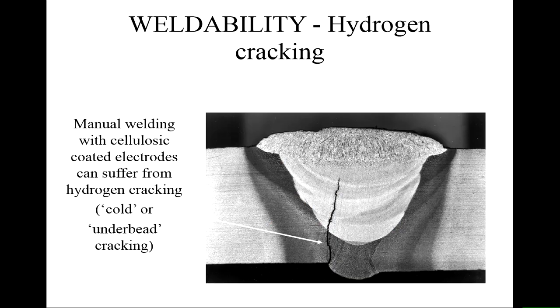So we can do something about that. And one of the things we can do is see what happens when you do the welds on site. And here's an example of manual metal arc welding with cellulose coated electrodes. So you can see the weld pass there, you can see a capping pass there, there's a root bead here, so this is a multiple pass weld. In fact, there's several passes in the fill here.